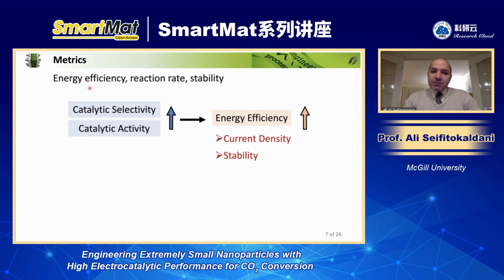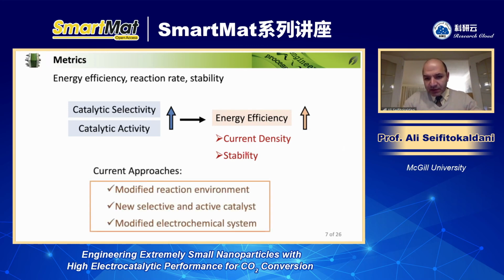So how can we improve these parameters? For energy efficiency, we need to improve the catalytic selectivity and also catalytic activity. Selectivity means if you are interested in producing ethylene, then just produce ethylene. Don't produce anything else. And we evaluate it through the Faraday efficiency parameter, which I'm going to talk a little bit more about. The catalytic activity means the energy input to the system, which translates to the applied voltage in our context. So you want a system which requires the smallest possible applied voltage, but at the same time is very selective, to improve the energy efficiency. Of course, you want to work at very high current density and also with a very stable system.